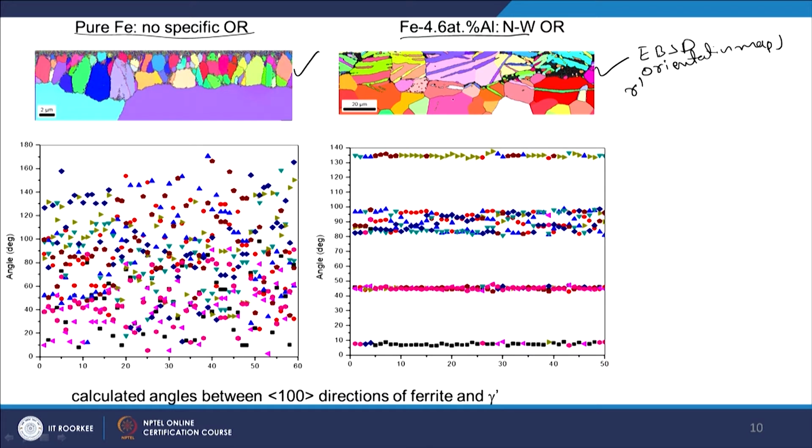Now, in both cases they are not only unusual plate-like, whenever they are forming like this, they are also always developing with a unique relationship with the orientation of the ferrite. Okay. Now, you see in this grain the ferrite orientation is given with one color, and in that you have one color, that means one orientation of iron nitride, and that changes here because now the orientation of the ferrite grain has changed, then this is coming up.